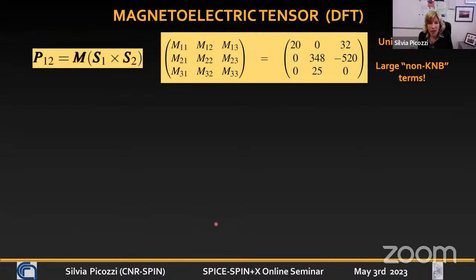And so what we got was actually that many elements were different from 0. And we have, of course, a small number. Well, this is in 10 to the minus something electron per angstrom, which is a difficult unit, but let's say, if you have barium titanate, which has about 30 microcoulomb per centimeter squared, here the polarization is orders of magnitude smaller. So you expect polarization induced by spin order to be small, and this is also what you get here. But it is intriguing that you have some kind of polarization below, again, the magnetic ordering temperature.